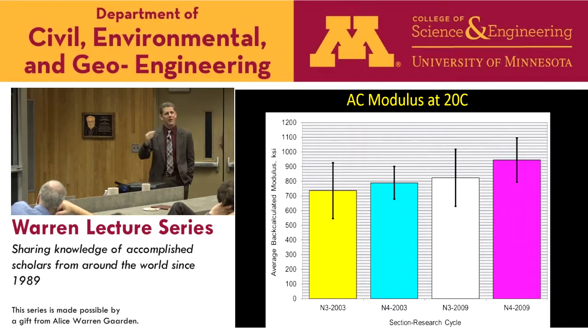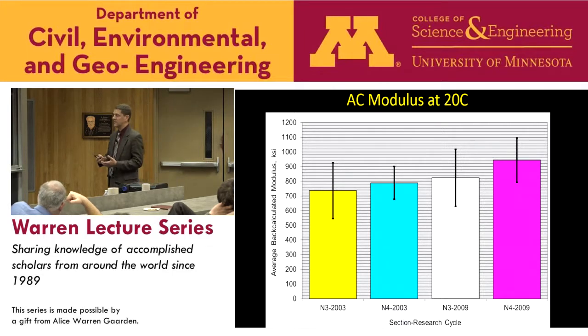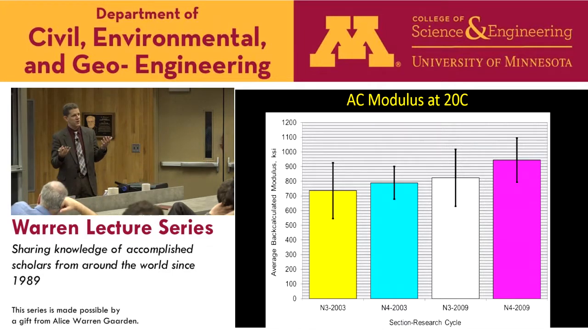So if it's going down, that's a sign that we probably have cracking occurring, or damage is accumulating, because it's not able to carry that load as effectively and the stiffness is decreasing. If it's staying the same, that means it's probably structurally healthy. And if it's actually aging over time and that binder is stiffening, what we'll see is an increase in the modulus, and that in turn gives us a reduction in the strain level.